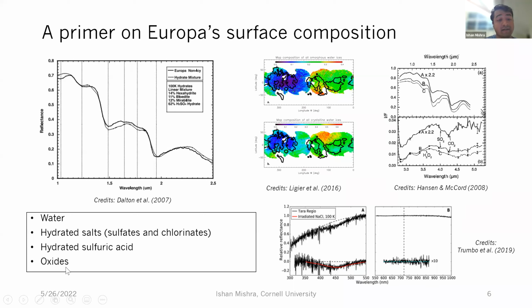And then oxides have also been detected. There are some sharp features at longer wavelength, but the detection has been tentative. But we also see some features in the UV and visible. Oxides are also expected because the surface is primarily dominated by water ice. The water is breaking up because of bombardment by energetic particles, and whatever reactions follow leave oxides as one of the byproducts of those reactions.